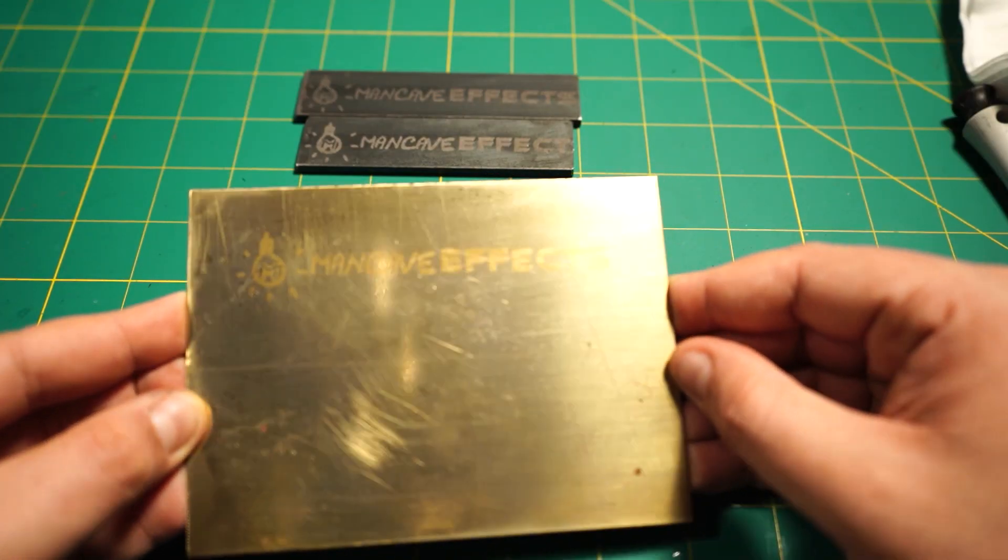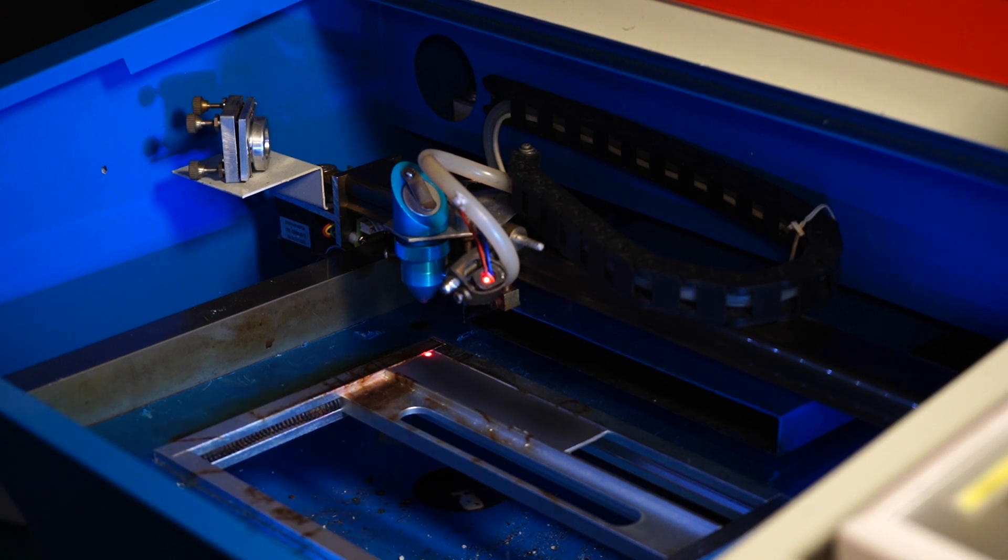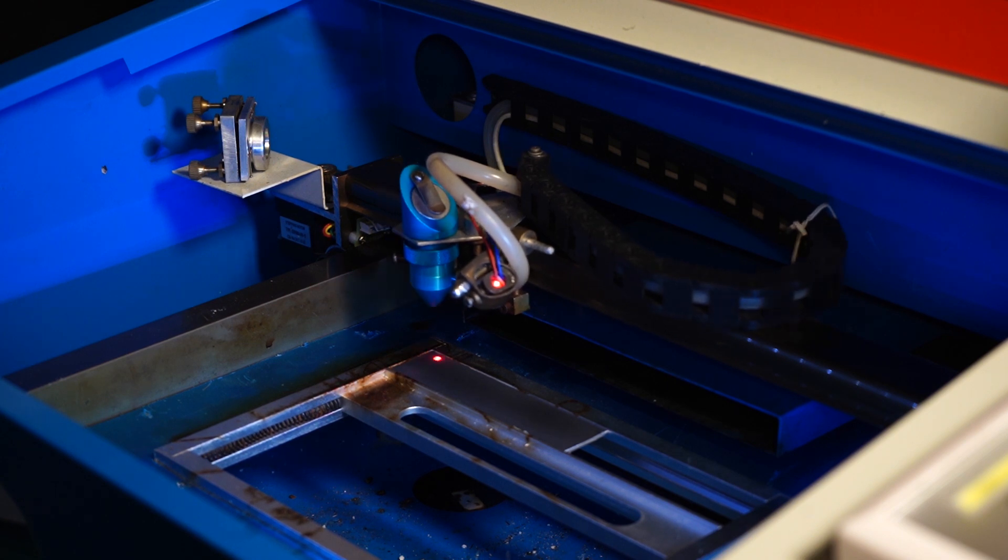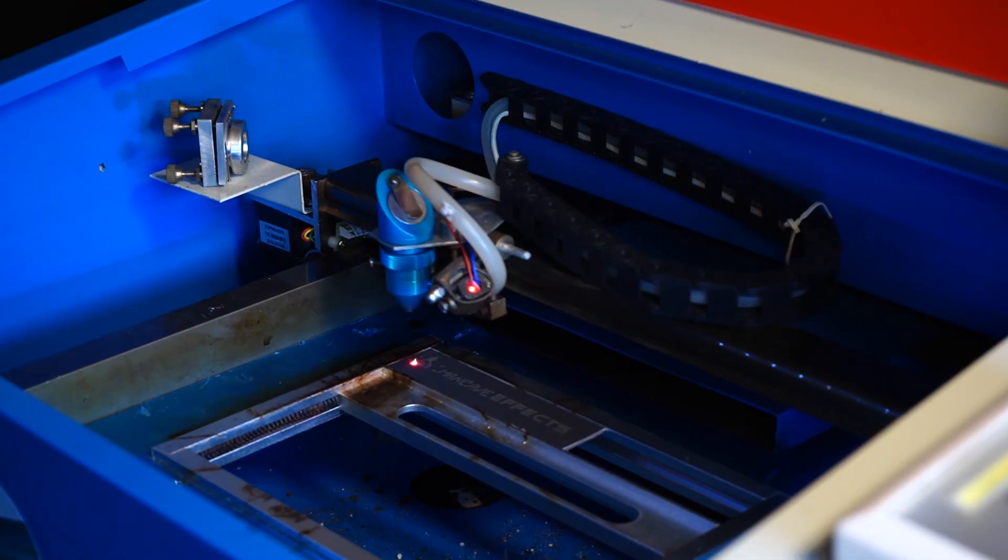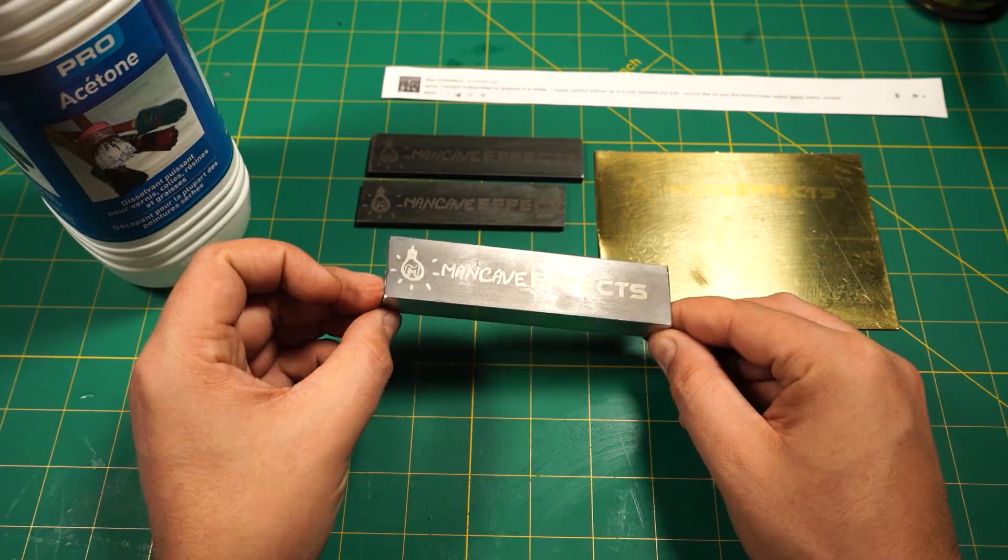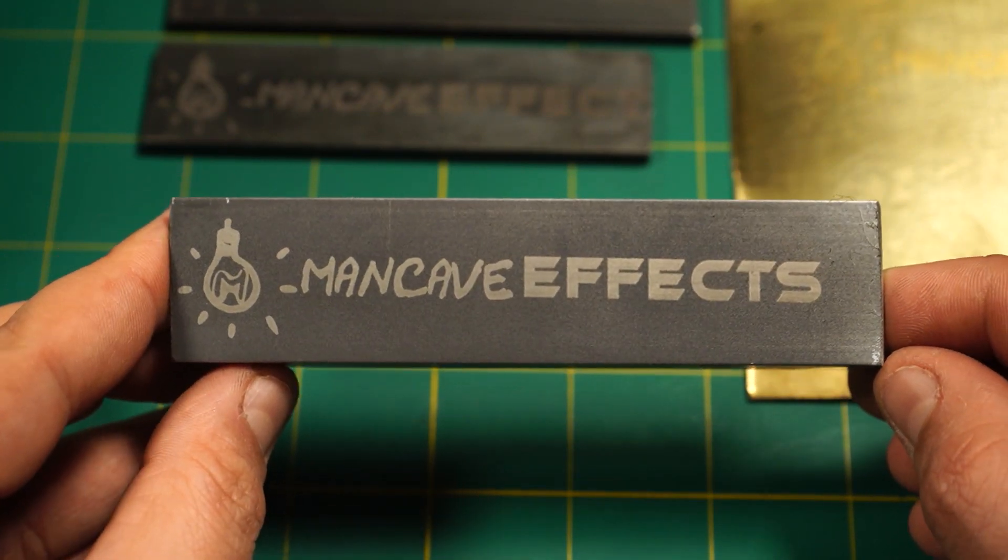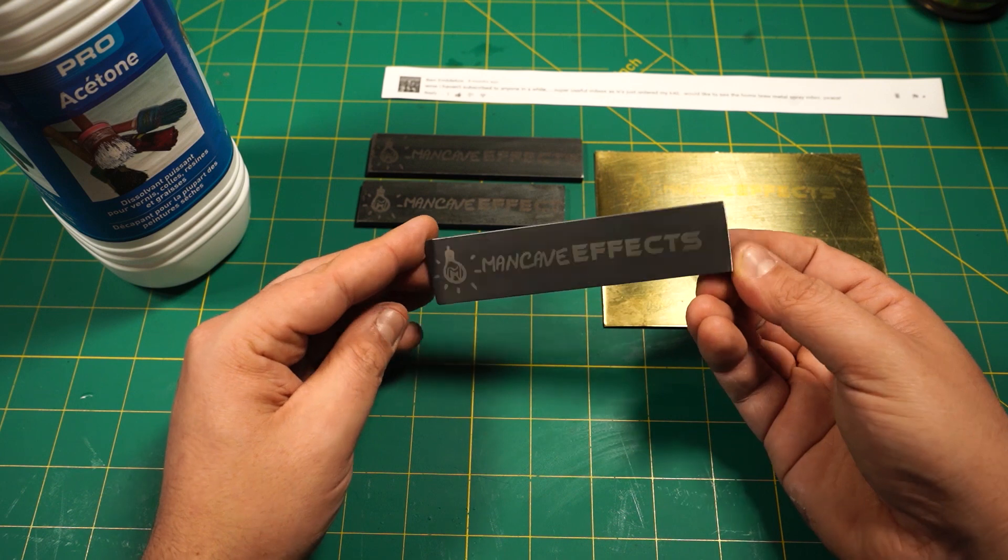Now you will ask, why aren't you trying aluminum? Well, that's because I am out of aluminum. No, I am just kidding. Let's try aluminum. If dry Moly Lube marks brass and steel, aluminum should be an easy game, right? I coated this piece with four thick layers of Moly Spray and as all the others I give it three passes with the laser. Now this looks awesome. Probably the sharpest and crispest marking my laser ever spit out. Let's get rid of the excess with some acetone.